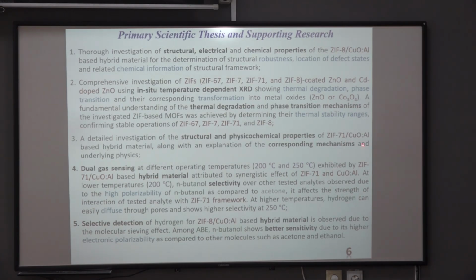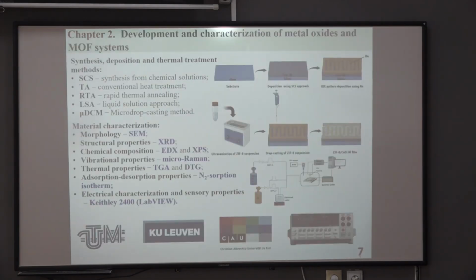In ZIF71 copper oxide aluminium structures, we go into detail on the physico-chemical properties investigation and correlate it with the sensing mechanism. Using this system, it exhibits dual gas sensing for N-butanol and hydrogen at different operating temperatures, and the underlying physics behind it is hydrogen selectivity due to the molecular sieving effect, and among VOCs due to the high electronic polarizability of target analytes.